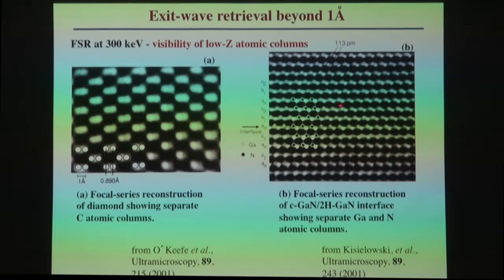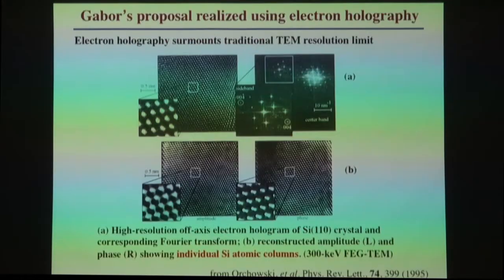And here is an interesting example, a focal series reconstruction of gallium nitride. If you read it off, you can see up here we have the cubic phase, the zinc blende phase, and down here we have the wurtzite phase, so it's ABABAB, and here it's ABCABC. You can read off the positions of all of the gallium and nitrogen atom columns, separated in this case by 1.13 angstroms.